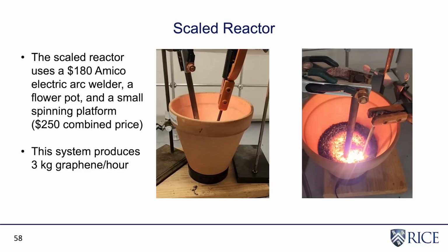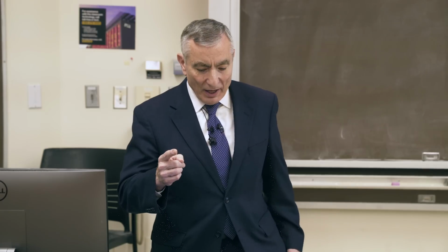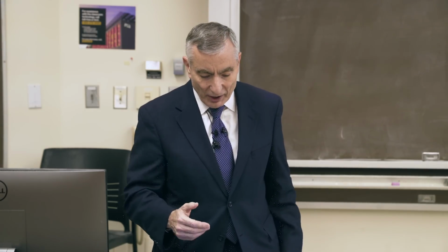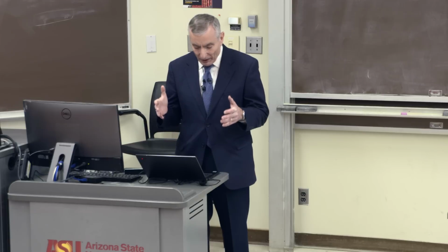And so here's the scaled system, and you can just take this flower pot and you just stir it around with the arc welder going. We bought a little turntable from Amazon and put this on there and just start spinning it around. And this system produces 3 kilograms of graphene per hour. 3 kilograms of graphene per hour. So you can make all the graphene that you need for your lab for a $125 arc welder, and well, this one we used the $180 arc welder and a flower pot and a spinning platform and 2 electrodes made of carbon. That's it. It's all you need to do this in your own lab.